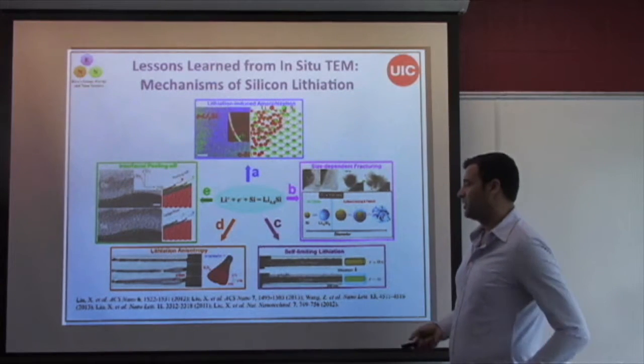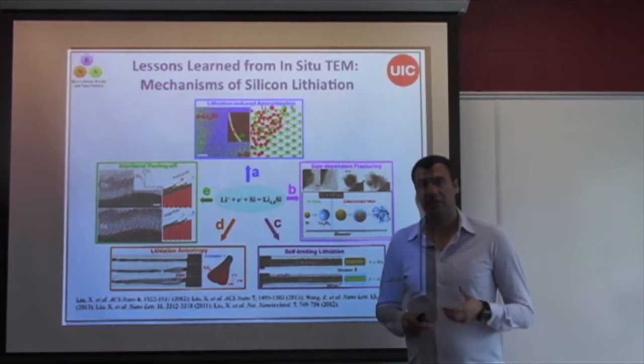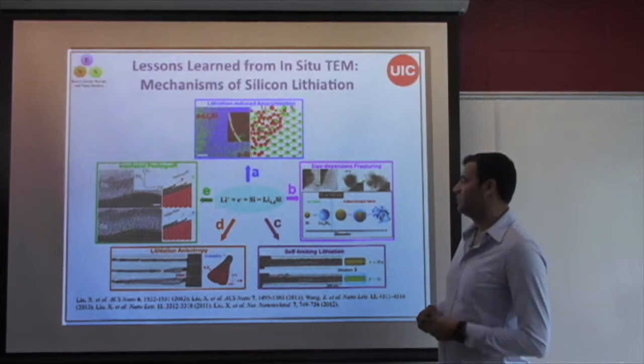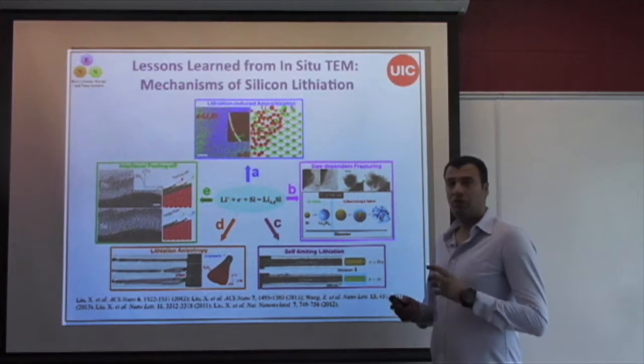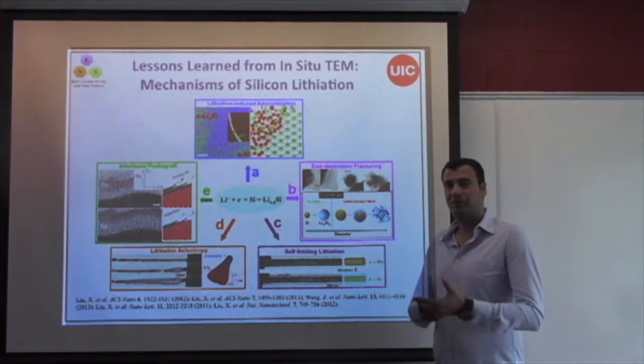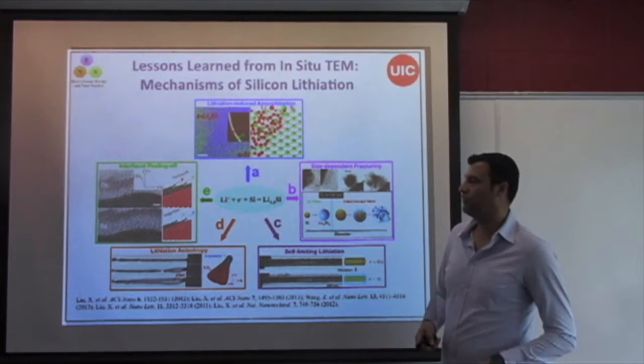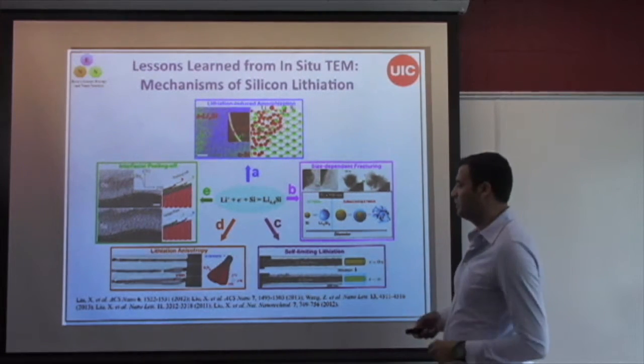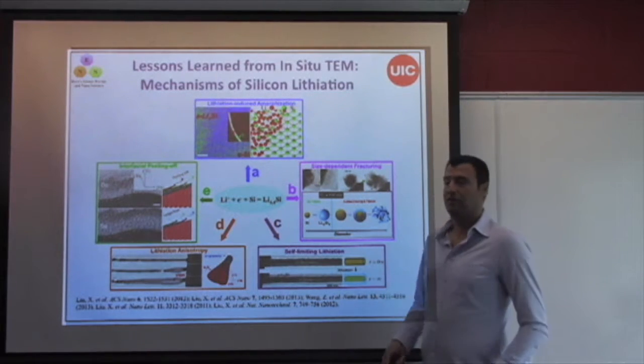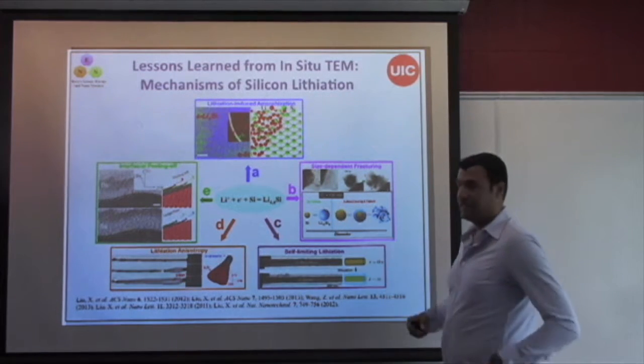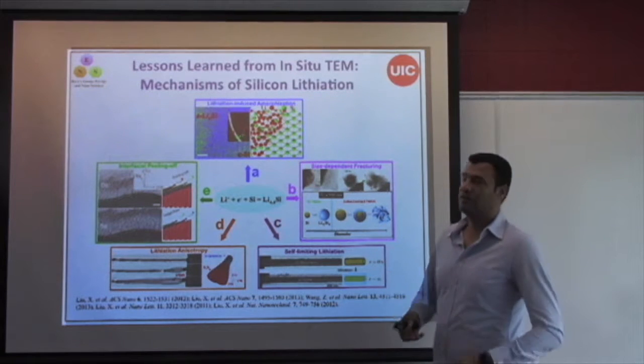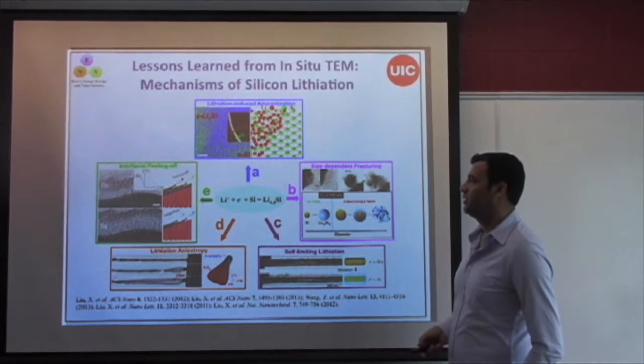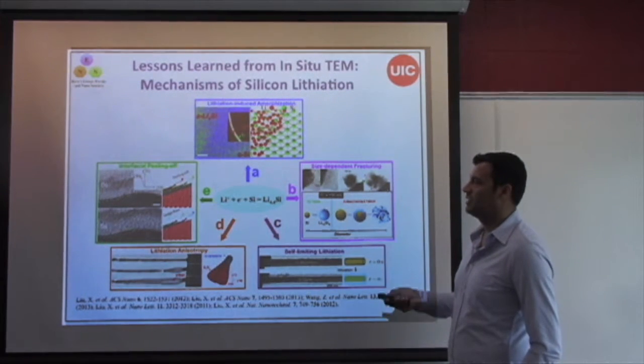Another observation was that there is a self-limiting behavior during lithiation, which is controlled by how much stress is being generated in the sample due to the progress of lithium into the material, which eventually might stop or maybe act as a reverse force driving away the lithium from the sample.